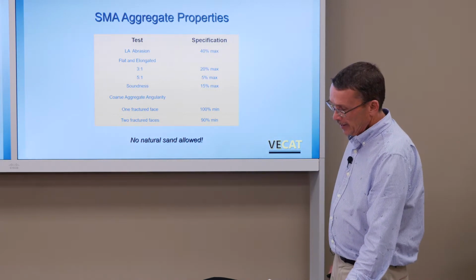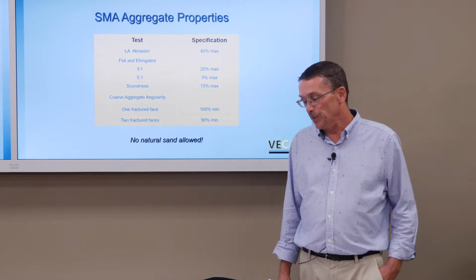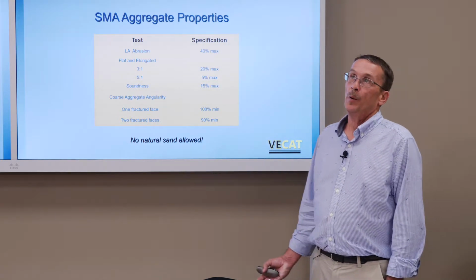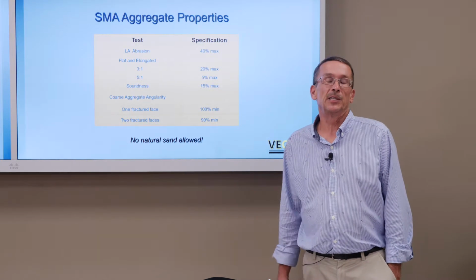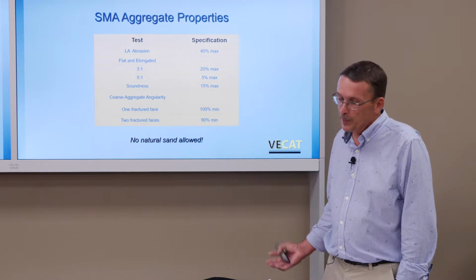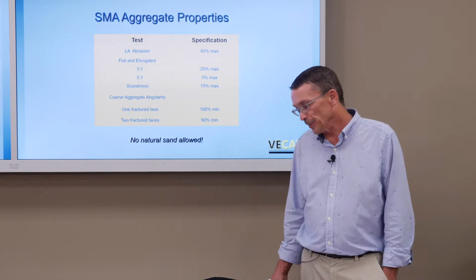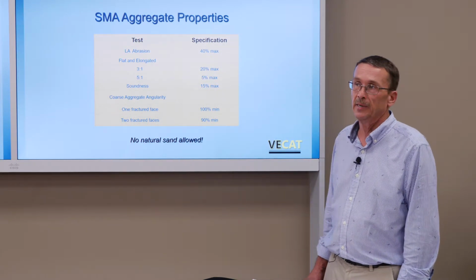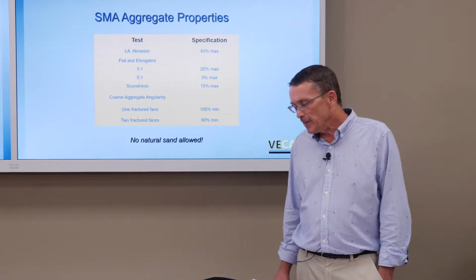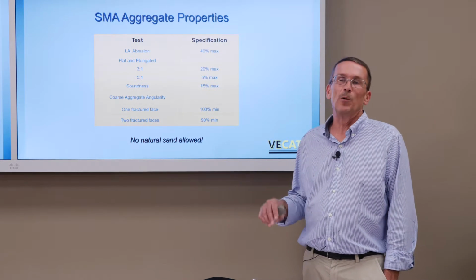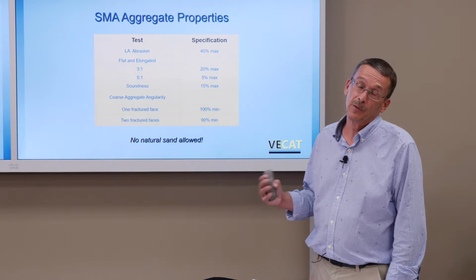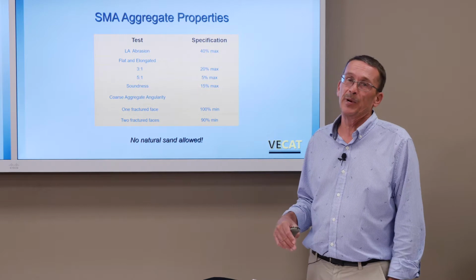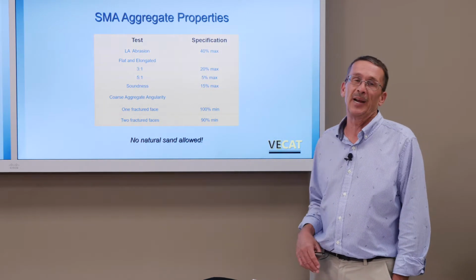Mineral filler, you are permitted to use and blend 2 mineral fillers. Typically, the SMA that I'm familiar with that we run, we use 1 mineral filler. Mineral fillers in the region where I work are kind of limited. The availability is not all that great. But if you choose to go with 1 mineral filler, or it doesn't matter if it's both, tend to use a mineral filler that has a high percent passing the 200.